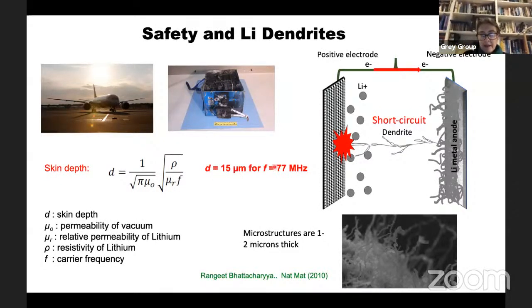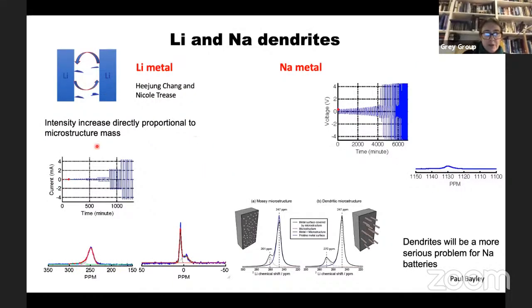For lithium metal at the fields we're using, so this is 77 megahertz, it's a 200 megahertz field for protons, we have a penetration depth of about 15 microns. What we did was use that to quantify how many dendrites are formed. So this is a lithium metal demonstration where we're looking at a symmetric cell.